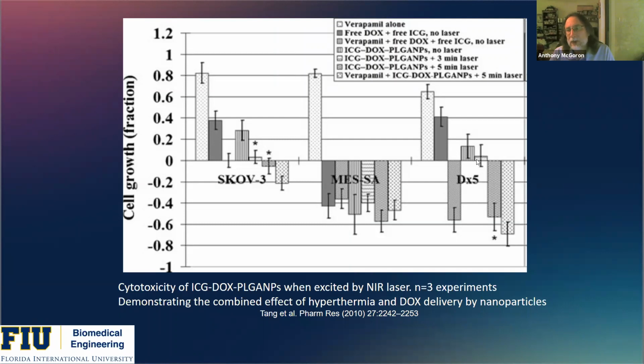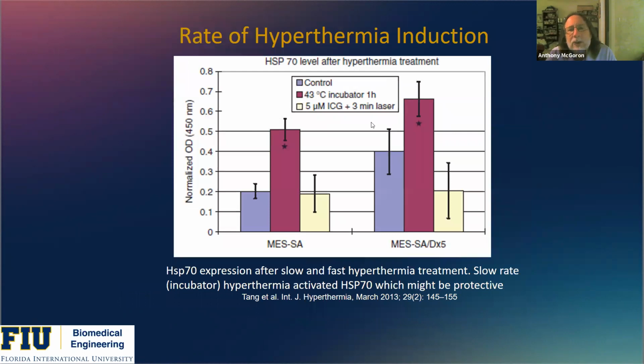But with nanoparticles, we can increase the uptake, but we also get a much greater effect if we also induce the hyperthermia. Here I show that the verapamil doesn't really add too much extra in terms of getting more of the drug into the cells because the nanoparticles are already bypassing the P-glycoprotein, so they don't need that extra boost. So here I'm just going to show one slide that relates to what might be happening on the oncobiology side of this fast rate hyperthermia. So what we did is we took the chemosensitive cell line, MESA, and the chemo-resistant cell line, the MESA DX5. And we exposed them to a 43-degree incubator hyperthermia over 1 hour, or the indocyanine green induced hyperthermia over 3 minutes.